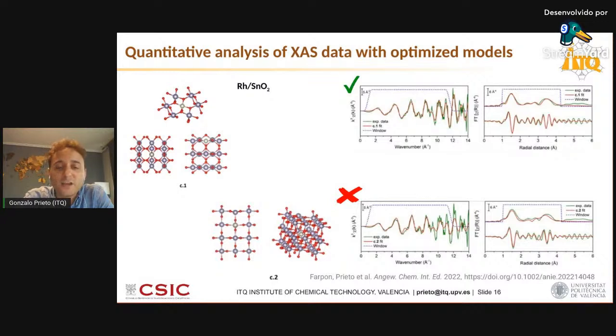But then when you place it in the bulk, the fitting is worse. Actually, it's a physically non-sensible fit, in the sense that some of the free fitting parameters take values which have no physical meaning. For instance, a Debye-Waller factor which is too high or negative. So that's a way of discriminating centers.